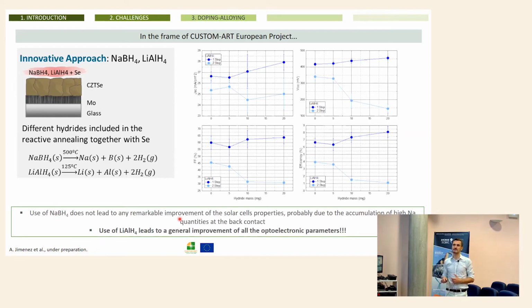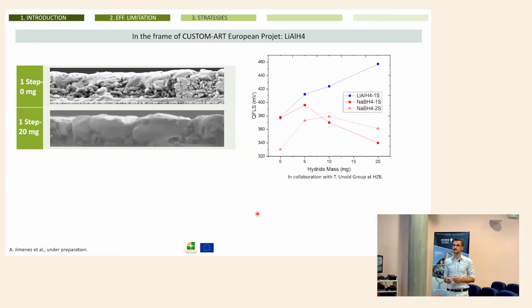In particular, the use of sodium borohydride doesn't lead to any remarkable improvement. This is mainly because we think that there's too much sodium in the system for kesterite. So we are trying to adapt and see if sodium borohydride can be usable. But for the moment, using this in the atmosphere introduces too much sodium and then deteriorates kesterite, because you need some given quantity. If it's too much, then you start to have a lot of problems in your material. But lithium aluminium hydride led to a general improvement of all these optoelectronic parameters.